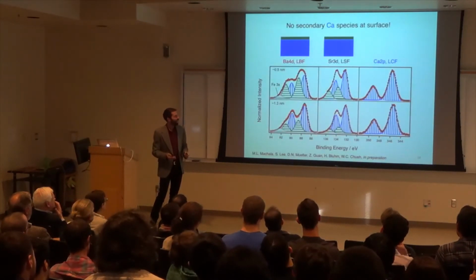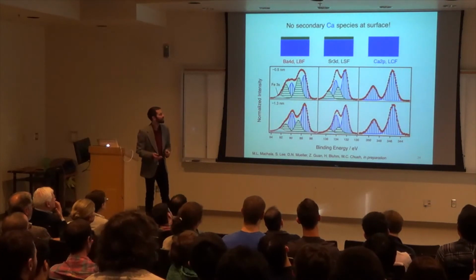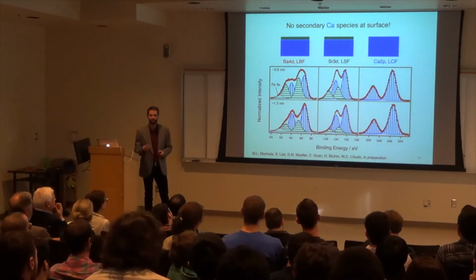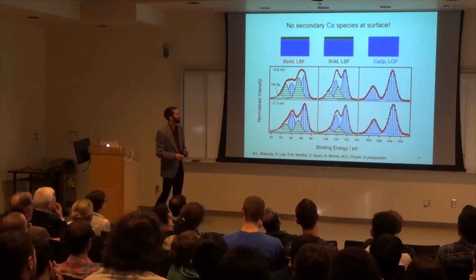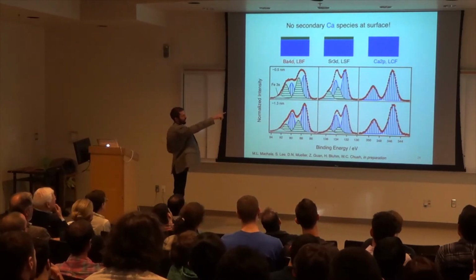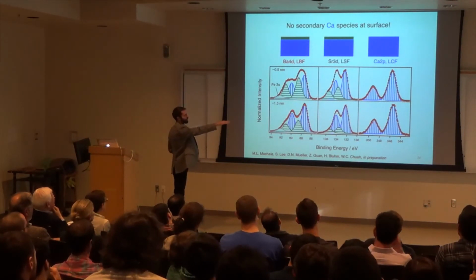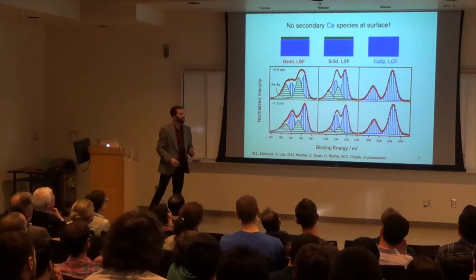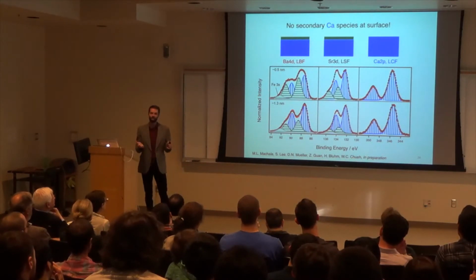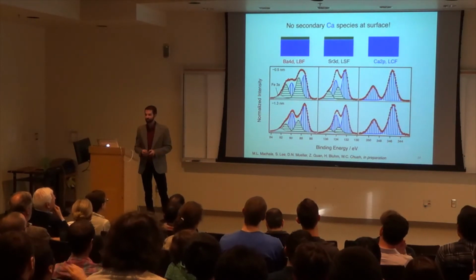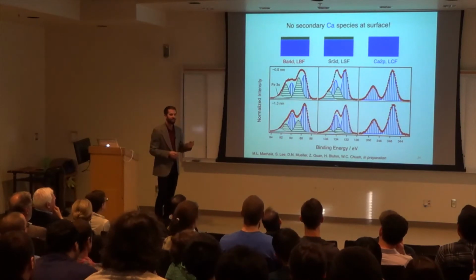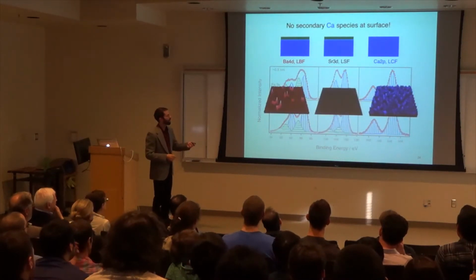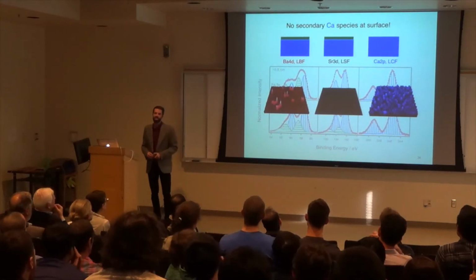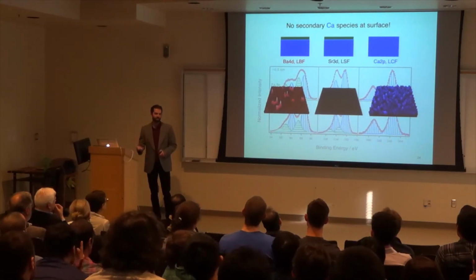But when we moved on to the calcium, what surprised us was that we didn't see anything in terms of a secondary phase, or secondary species. As you can see here, from surface sensitive to bulk sensitive, the spectrum doesn't change much. So this says that calcium is found all in one environment. That was confusing for us for a little while, because recall that what we saw with the surface is kind of bumpy. But we realized that's more a result of how we deposited the film. That's just how the film grew.